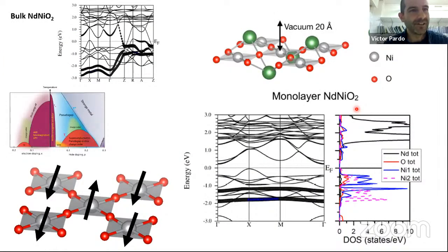Okay, so we know that when we dope them, they become more cuprate-like. But what about this point in the phase diagram? Do we have an antiferromagnetic insulating phase in these nickelates at all? Does it exist at all? Well, the bulk neodymium nickel O2 is paramagnetic and it's metallic. We have these hugely dispersive bands that cross the Fermi level. But what happens if we just grow a single layer of neodymium nickel O2?